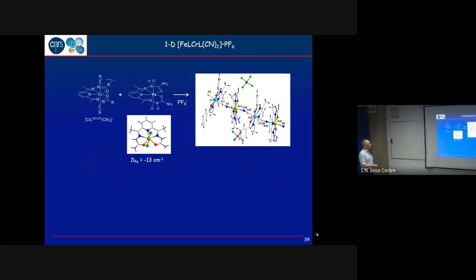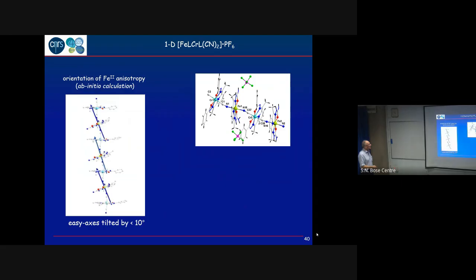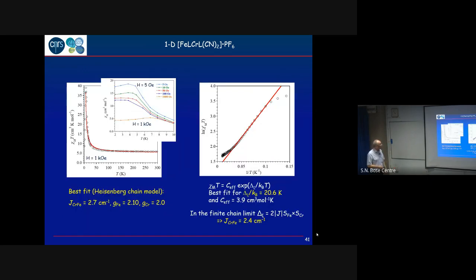So we have the same kind of arrangement. I don't want to detail that. Here you can see this is the local anisotropy of each of the centers, and what you can see is they are pointing really in the same direction. So the tilt between these is very small, so they are almost in the same direction. Here we have again the same behavior I have shown before.